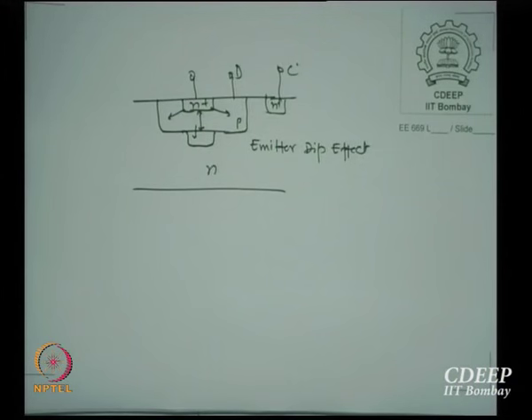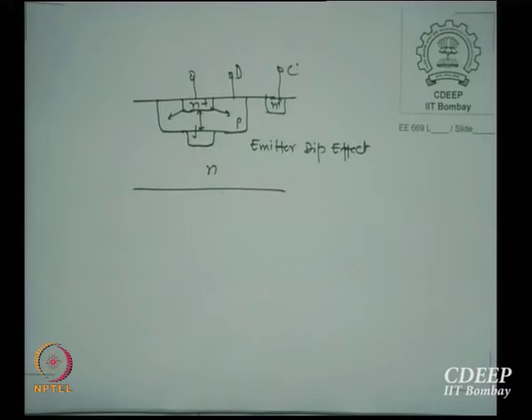So we figured out that the emitter is a heavily doped material, N plus, maybe phosphorus or something. What kind of vacancy pairs can it form? Phosphorus, or even arsenic, can form V minus and V minus minus pairs. So there is a diffusivity which is essentially available with this. But as soon as it tries to go below, the concentration itself reduces. Surface is highest, but as emitter diffusion happens, the concentration at this junction point becomes smaller and smaller. So at what time was this pair formation declared by us? When N is larger than Ni. But as N decreases, these pairs do not remain paired and vacancies are released.